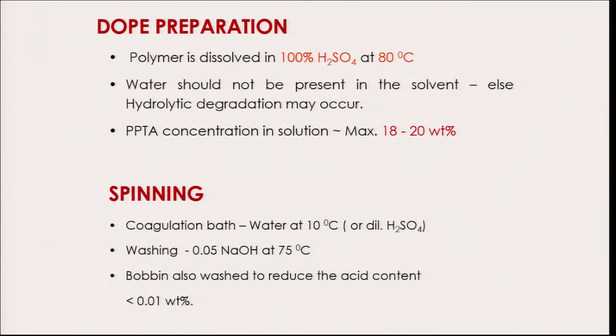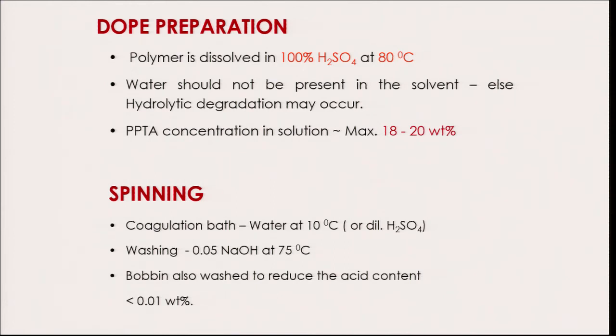The coagulation bath can be water or it can be dilute sulfuric acid, because I have dissolved it in sulfuric acid. So, the coagulation bath should have a non-solvent. And another point to note is, importantly, the fibers must be washed thoroughly by dilute alkali, that is to neutralize the fibers, to remove the residual acid from the fiber. So much so that the bobbins are also washed to reduce the acid content to less than 0.01 weight%.